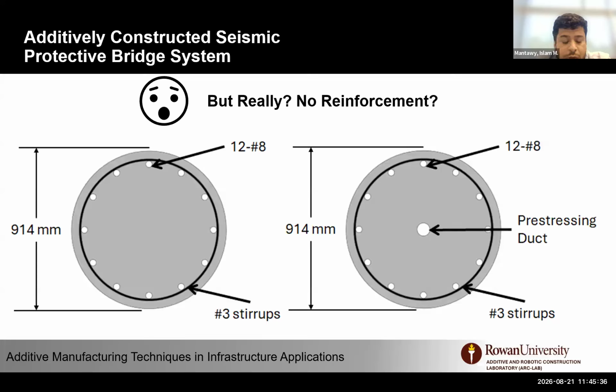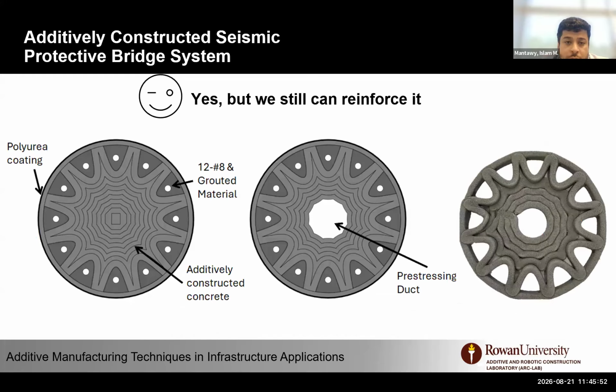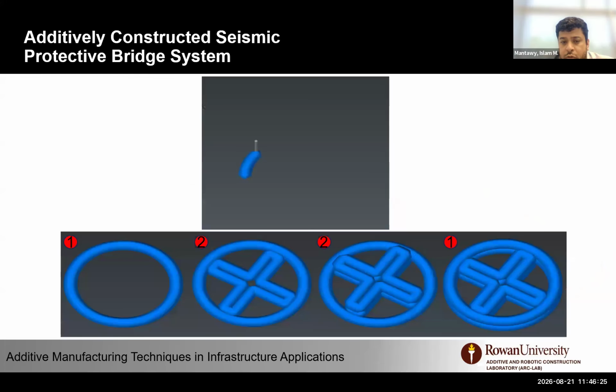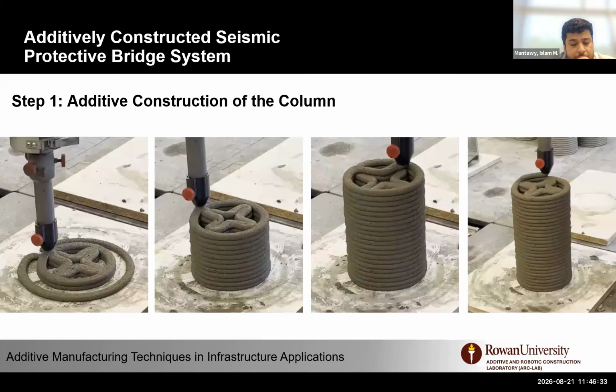So go back to the column. The way we reinforce our bridge columns or general concrete columns is by having longitudinal bars and spirals. Or in prestressing, you will see a cavity or duct to do the post-tensioning or pre-tensioning. So our goal here is actually to print the majority of the column, leave channels or cavities for rebar to be bonded, leave openings for post-tensioning, and for the spiral, we try to use an external confinement technique. I know Dr. Nani is well known for FRP and other work, so there can also be an option to wrap those columns with FRP. So the idea here is to print the majority of the column. Our column is just 6-inch diameter, so basically you iterate on the printing process here and print the columns.